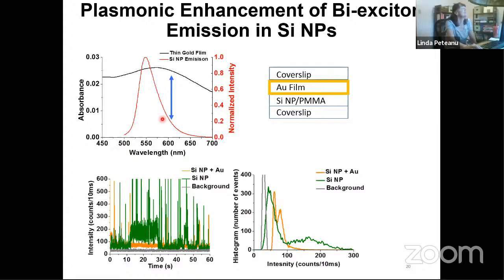This shows the overlap between the plasmon of the particle of the gold film and the emission band that we ascribe to the biexciton. And this shows another photon trace where now one can see that the dim emission is enhanced on gold versus on glass. And there's a quenching of the bright emission here. And that's also seen where basically this bright emission band here is quenched when we go to gold, and the low intensity emission is enhanced.